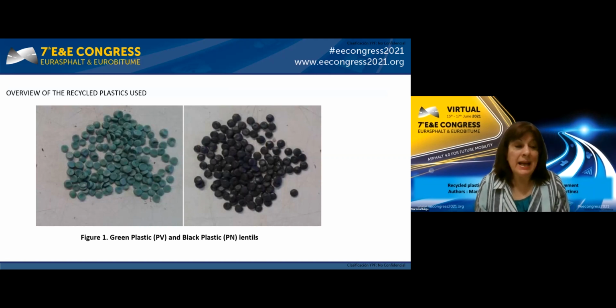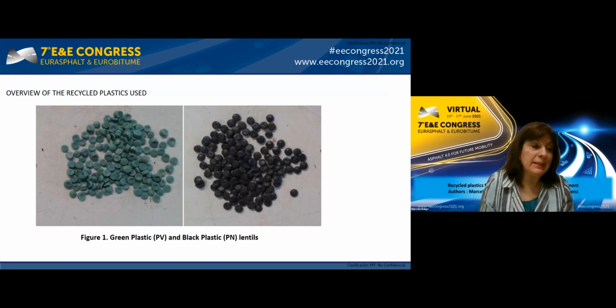The green plastic analysis made with the scanning calorimeter showed that it was composed mainly of high-density polyethylene. The black plastic lentils coded PN in this study were obtained from the recycling of silo bags. The silo bags are usually used in Argentina to provide low-cost temporary hermetic storage for grains. The black plastic analyzed by scanning calorimetry was determined to be composed mainly of low-density polyethylene.